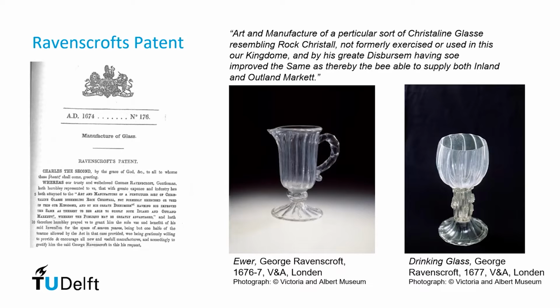And a very telling example is the glasses produced by George Ravenscroft in the UK in the 17th century, where he actually made a patent for a specific glass production process. But 2 years after he filed the patent, he added something to his patent saying that he had changed the recipe because his glasses would start to crizzle and spoil, basically meaning that they were degrading in this very short time scale even. And those are some objects that we now see as problematic, which are very heavily degraded. So the early Ravenscroft glasses are often problematic in museum collections.